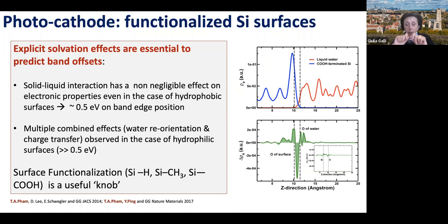And the other thing that we learned, that was already apparent from certain experimental results but we could actually quantify, is that surface functionalization, and we did calculations for hydrogenated, methyl terminated, and COOH terminated surfaces, can be used as a knob to move the bands in a way that is desirable for the transfer of charges. So this is an important finding.